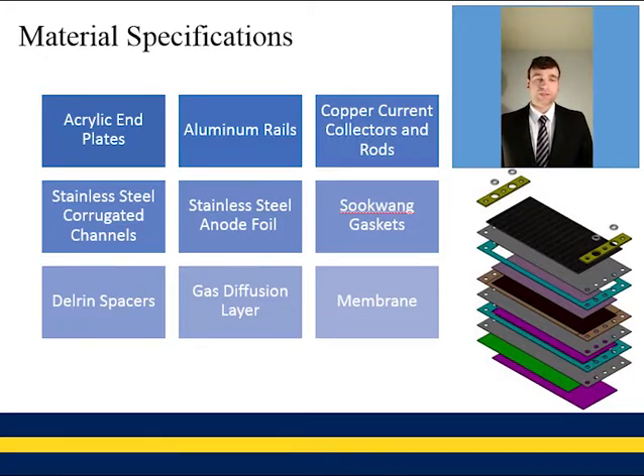Our current collectors are one of the most important parts of the cell because this is where our output is actually taken from the cell and applied. So we used copper because copper is extremely conductive. Stainless steel was chosen for our corrugated channels and foil because stainless steel is extremely corrosion resistant and is a good conductor as well. Sugru is a thick adhesive which seals well. This is why this was chosen as our gasket material.